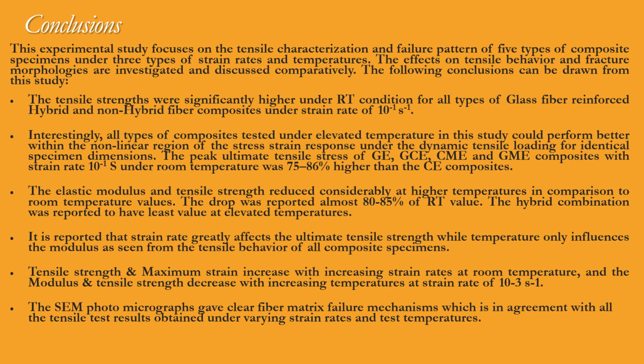The elastic modulus and tensile strength reduced considerably at higher temperatures in comparison to room temperature values. The drop was reported almost 80 to 85% of the room temperature value. The hybrid combination was reported to have least value at elevated temperatures. It is reported that strain rate greatly affects the ultimate tensile strength, while temperature only influences the modulus as seen from the tensile behavior of all composite specimens.